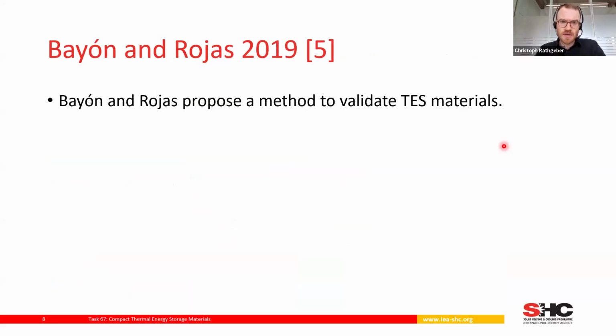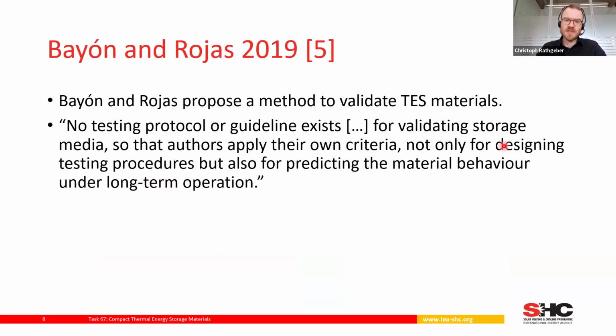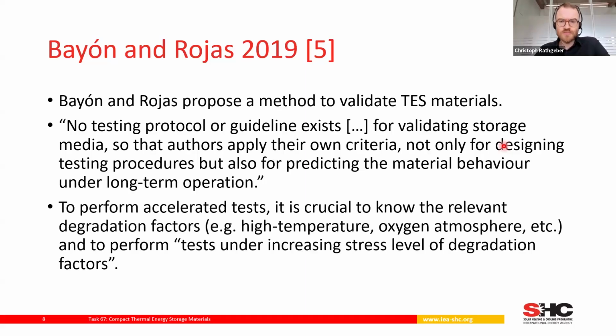The first example was by Bayon and Rojas. They proposed a method to validate these materials, and I would like to cite one of their statements. They say that no testing protocol or guideline exists for validating storage media. The consequence is that the authors apply their own criteria for designing testing procedures, but also for predicting the material behavior in the long run. Then they conclude that to perform accelerated tests, it is crucial to know the relevant degradation factors. That can be high temperature, oxygen, atmosphere, and so on. And then to perform tests under an increasing stress level of degradation factors.